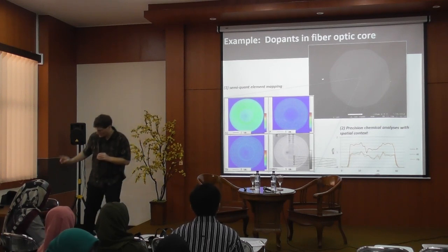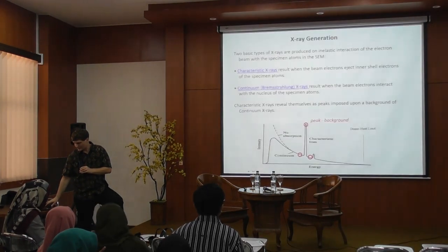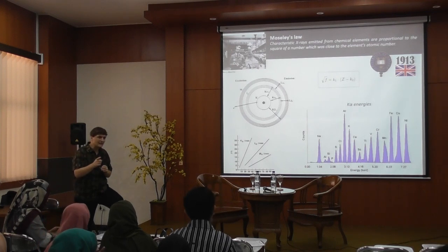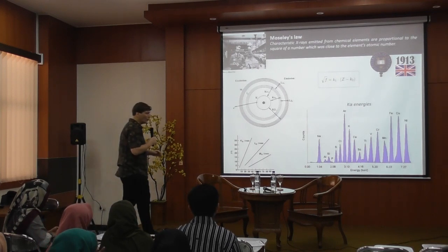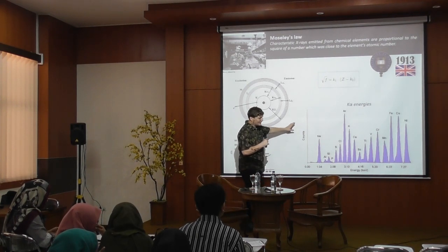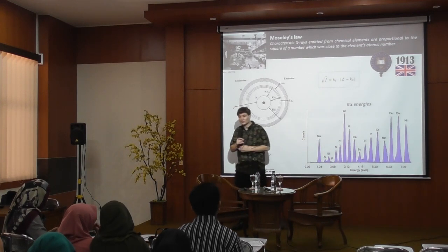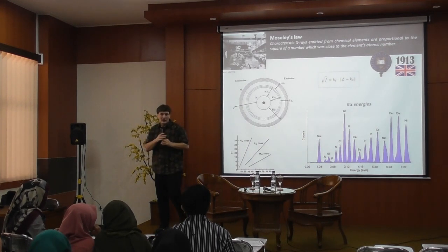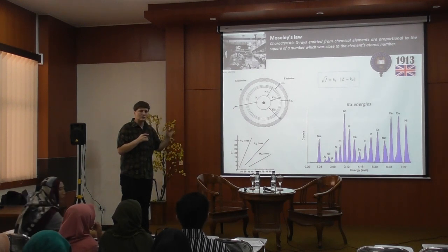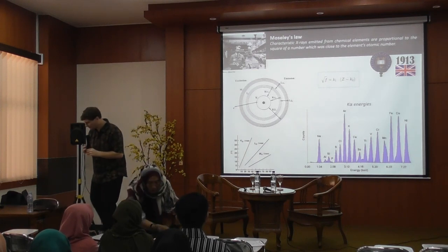So the difference between an EDS and a WDS, it works on the same principles. It's almost exactly the same thing. I guess the advantages to the EDS over the WDS technique are that you get all of the x-rays at once with the EDS. You get a complete analysis. You get this whole spectrum, which is advantageous, especially if you don't know what's in there. And then you can deconvolve the spectrum. In most cases, you can get a reasonably good quantitative determination, at least a semi-quantitative determination.